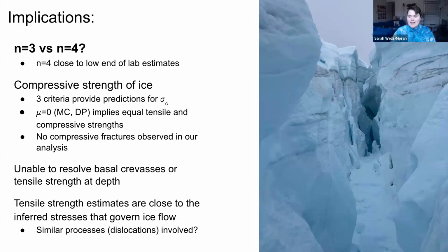Last interesting point is that tensile strength estimates are pretty close to the inferred stresses that govern ice flow. So if you go out and calculate stresses on an ice shelf using n equals 4 or n equals 3, all of the stresses that you find are within 50 to 100 kilopascals of the tensile strength estimate. So this potentially implies that there are similar processes involved in ice flow versus ice fracture, and potentially dislocation tangles or pileups could be involved in fracturing. So that could be a very interesting mode to pursue in the future.